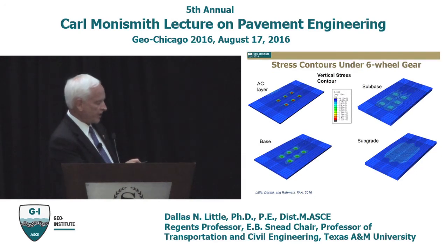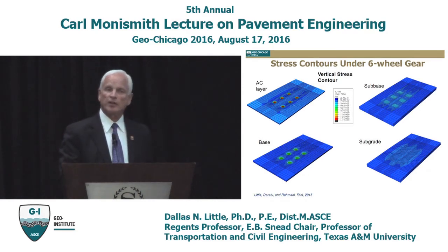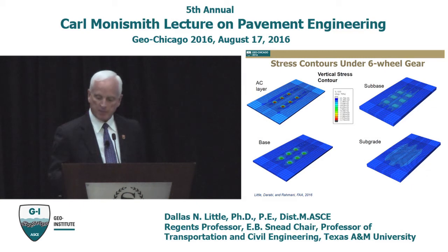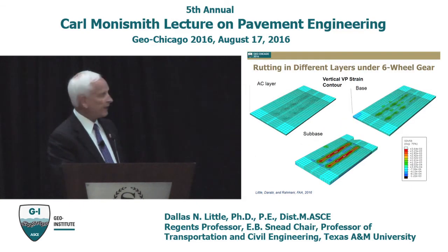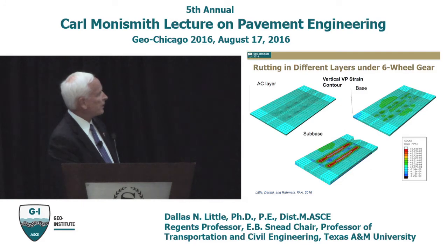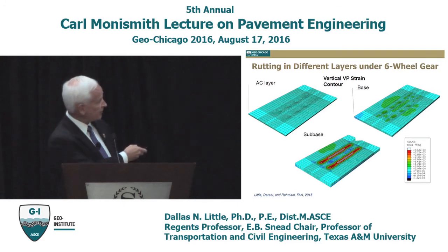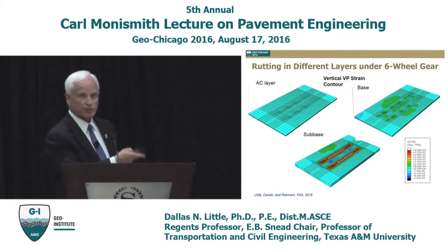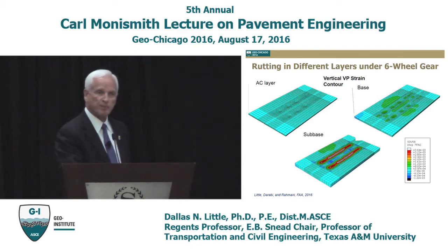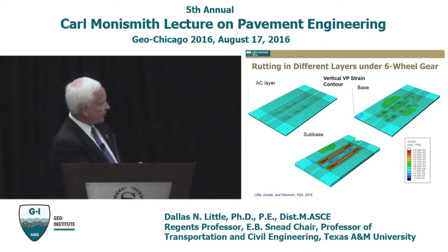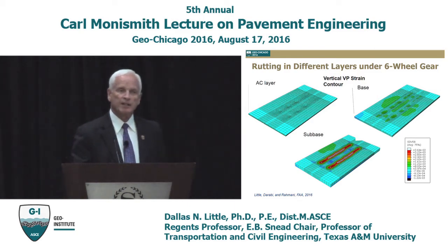But you can see, of course, that the vertical stress contours are high in the asphalt layer and very, very low in that subgrade, which is like a CBR 3 subgrade. But yet, according to PANDA, if you look at the viscoplastic strain that occurs in the pavement layers, even though those vertical stresses are high, the viscoplastic strain in the asphalt layer is negligible because it resists it, according to that plastic deformation model. But down here in the subgrade is where you really have the high viscoplastic strain. So that's where the rutting is occurring.